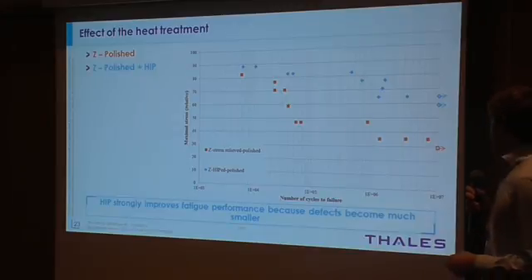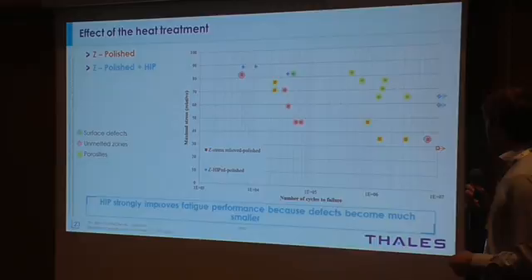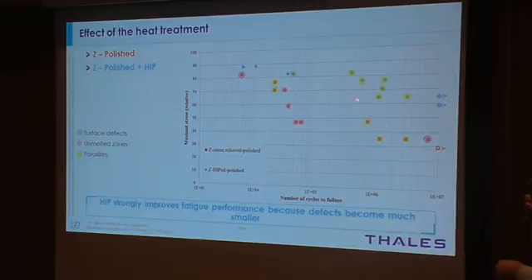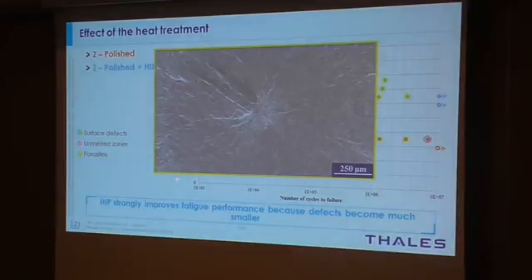And last, we looked at the effect of the HIP. So here we can see that HIP specimens also failed from porosities, but the fatigue properties are higher than not HIP specimens. And this is explained by the fact that the porosities in unmelted zones are often closed defects. So here is an example. It's a sort of closed defect or porosity, and so the defect is very small, and the fatigue properties are higher.